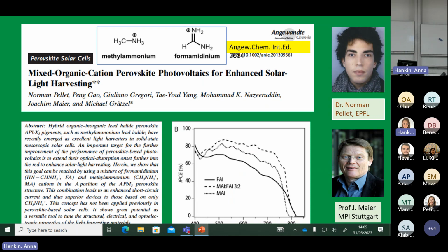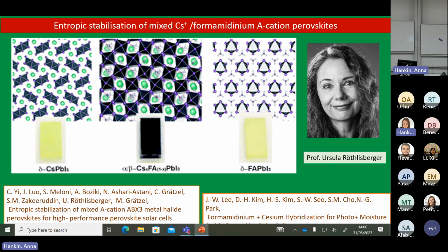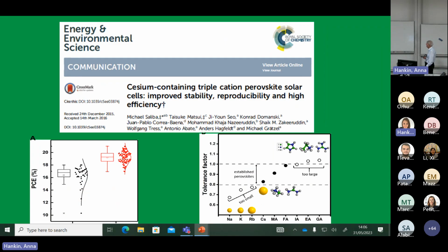One way is to just mix the methylammonium with formamidinium. That was our first paper, and today a lot of highly efficient perovskites still use that mixture. Methylammonium stabilizes the formamidinium. Or if you use cesium, you can also stabilize it. So here you have the two delta forms of formamidinium and cesium. When you grind them up, they turn black, and you get the mixed stable black form.